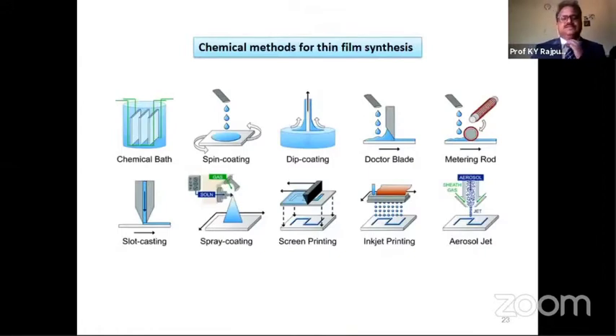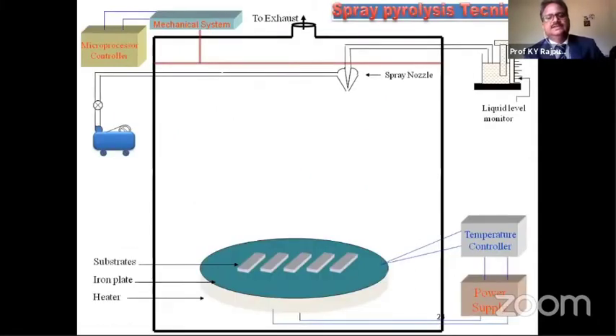So far as the preparation of this electrode material is concerned, there are various methods of preparation of the catalyst, and these are the chemical methods, particularly chemical bath, spin coating, dip coating, Doctor Blade method, metering rod, slot casting, spray coating, screen printing, inkjet printing, and aerosol jet. Of these, we effectively prefer to use the spray coating technique, where the interface between solution and gas is used to form very fine droplets, and these fine droplets are spread over the hot substrate, resulting in a pyrolytic reaction, and the thin film forms.